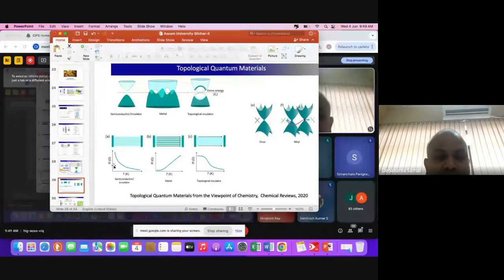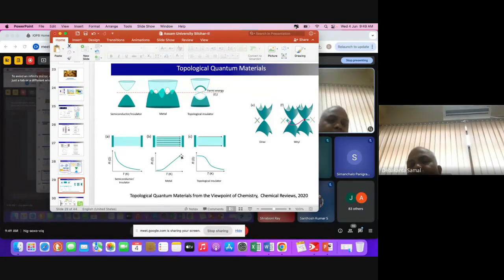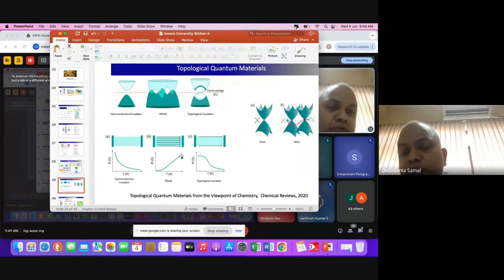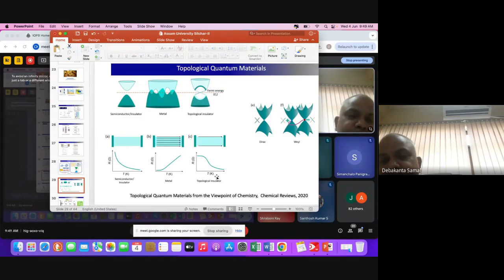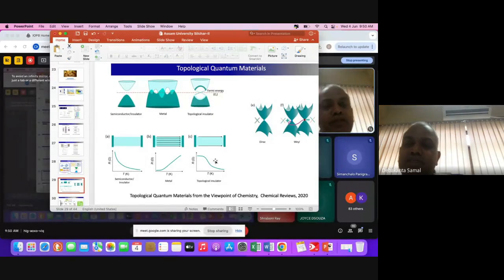And this is what you see if you look at the resistivity versus temperature. For a semiconductor and insulator, it increases and diverges at T equal to 0. For a metal, the resistance increases as you increase the temperature because of other scatterings, like electron-phonon scattering at high temperature. For a topological insulator, because the bulk is insulating, it shows insulating or semiconducting behavior, but at low temperature the surface conduction dominates, so it gets saturated. This is what a topological insulator is.